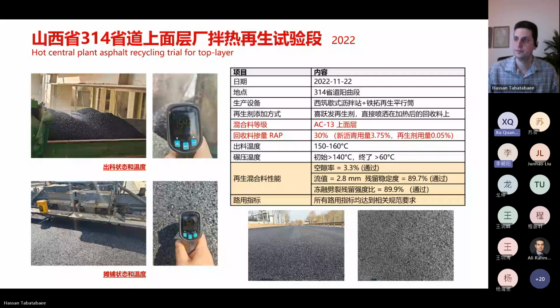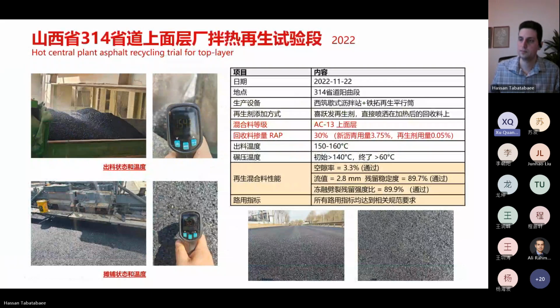The performance for now is all very good. And also starting from last year, we started to cooperate with Rio in Beijing, and they have this in situ hot recycling for porous asphalt in Zhejiang province. This is also the first time in China that we have ever done this hot recycling for porous asphalt, also in the surface layer, top layer. The reason they chose our rejuvenator is also because it's a combination of recycling but also warm mix. Because in the past they actually needed to use two components, one rejuvenator and one warm mix additive.